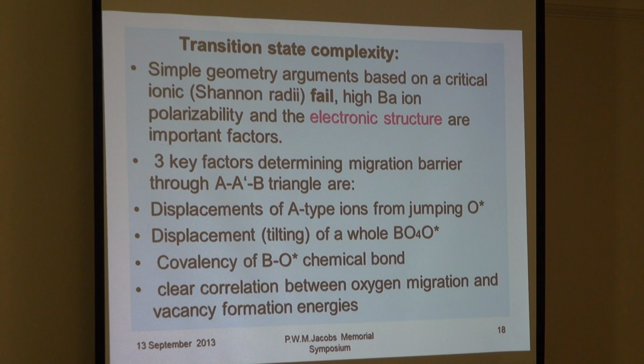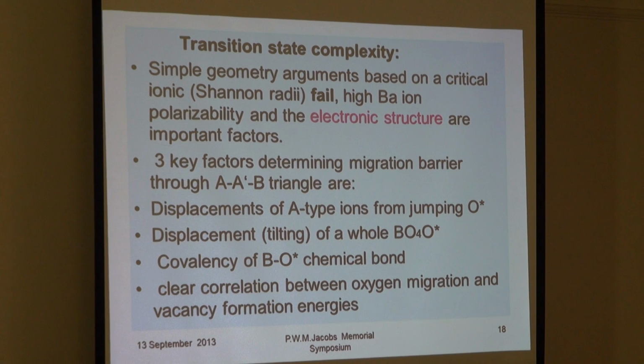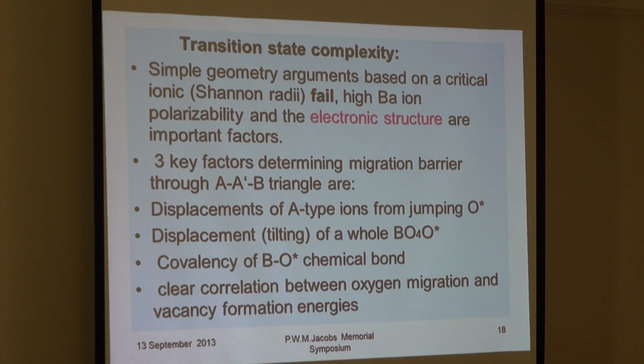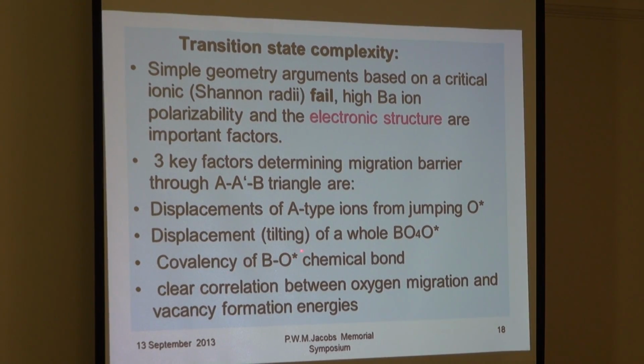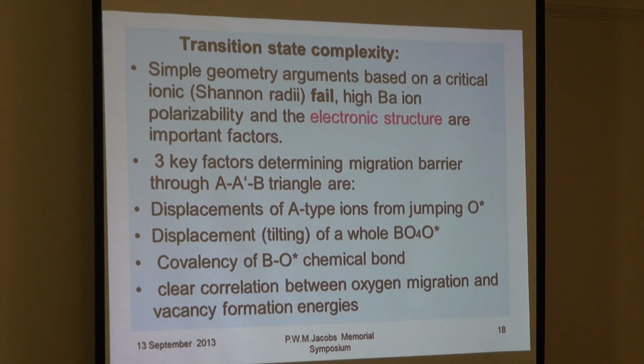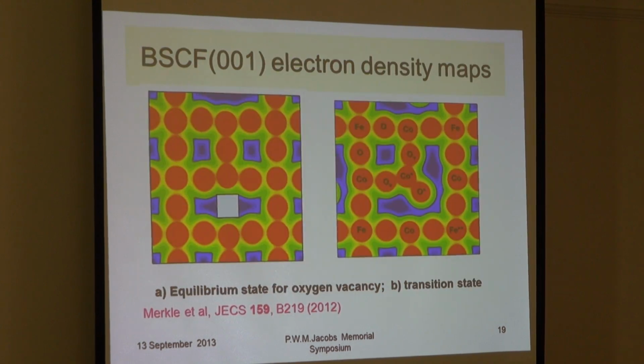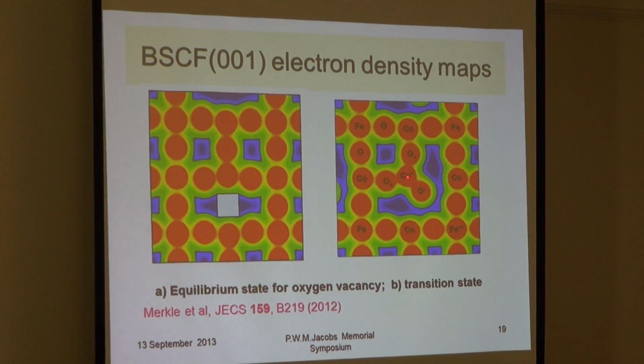So it's not even local, but it's a distortion which covers some local volume of several tens of angstroms. And as I mentioned, there is also important covalence, and change of covalency, between the B-type cation, cobalt for instance, and oxygen going through the saddle point. So this is just a sketch of the electronic density distribution when the vacancy jumps into this position, and this is the transition state. The covalence between these two, and charge transfer, just controls the migration energy.